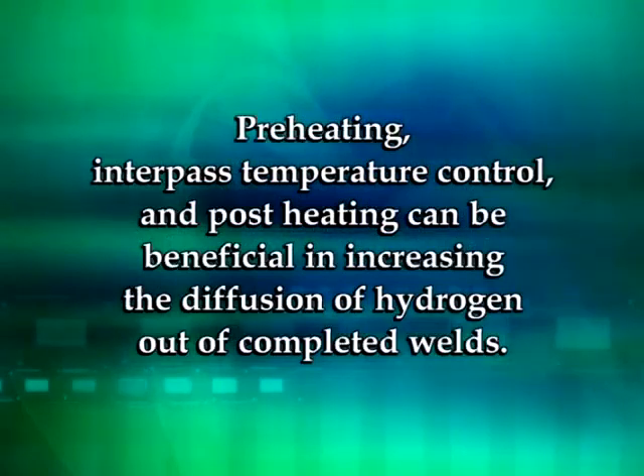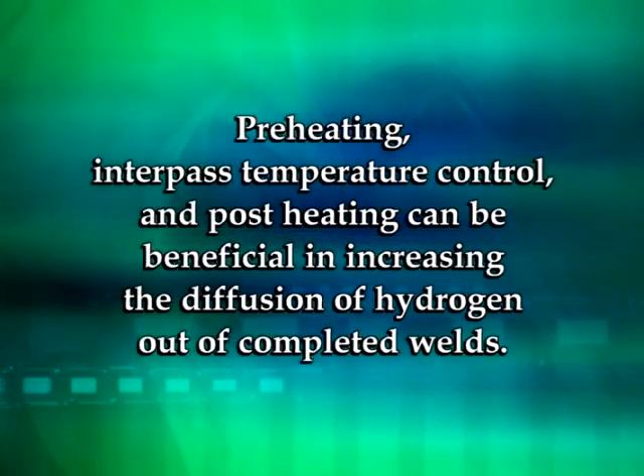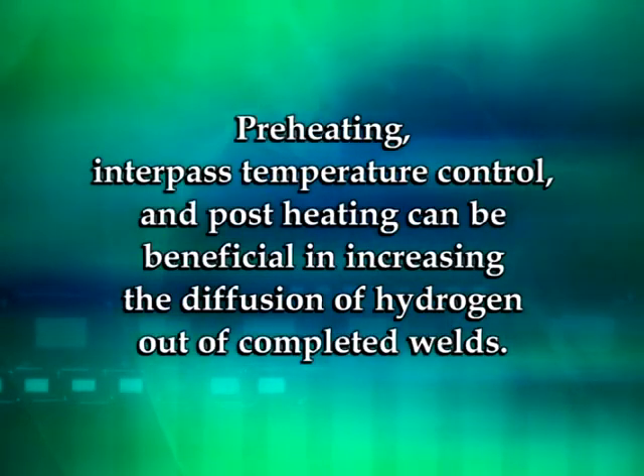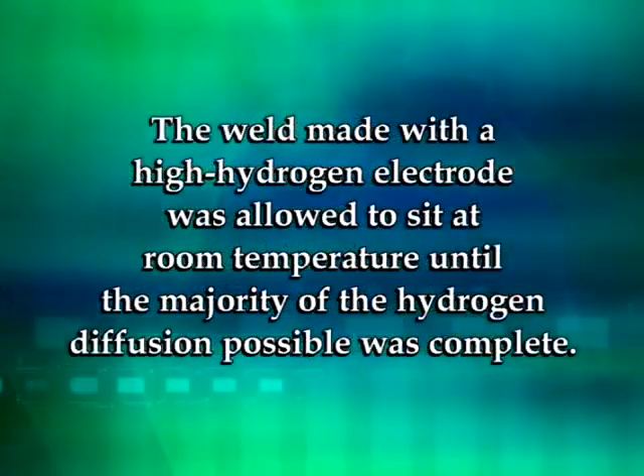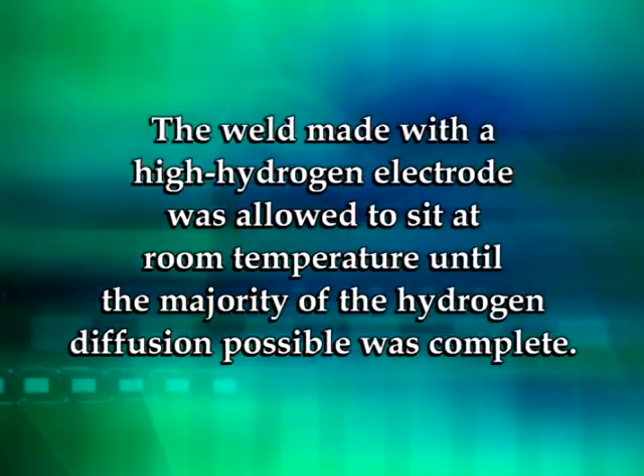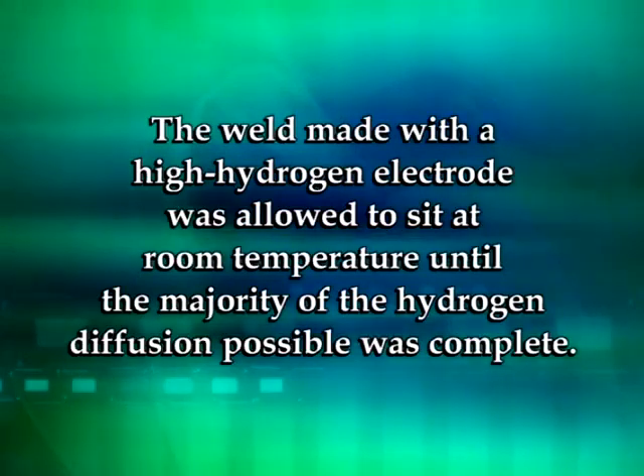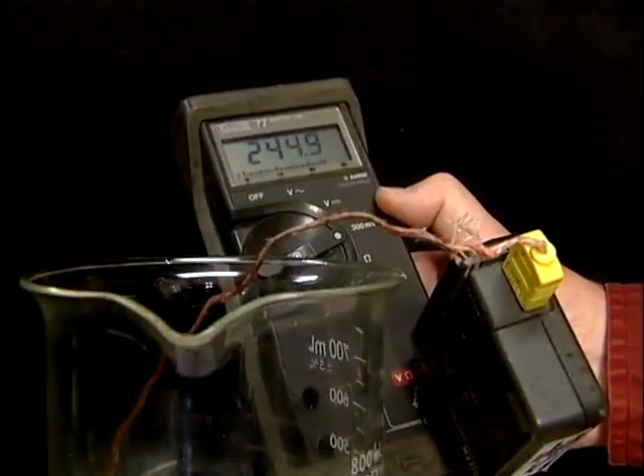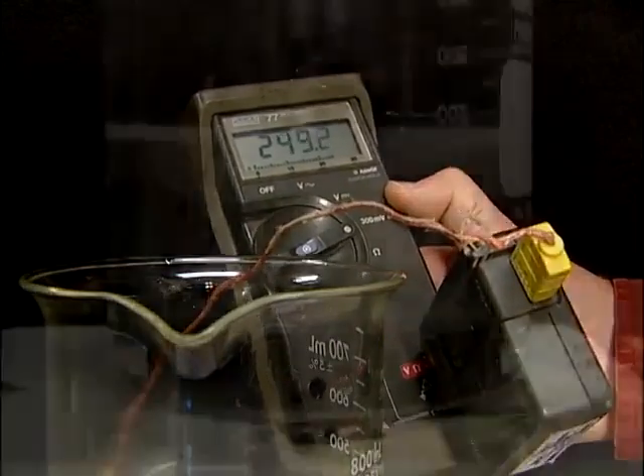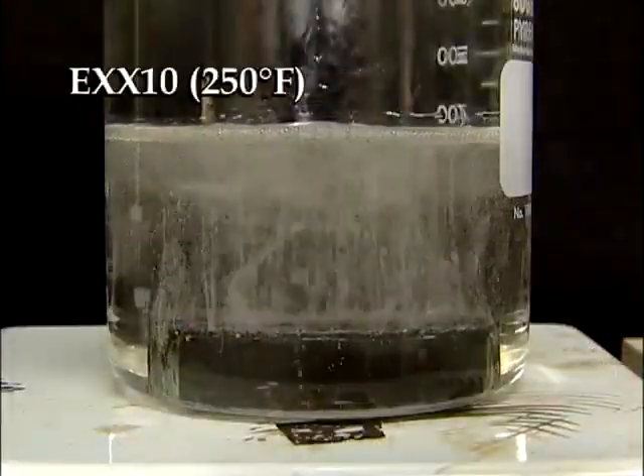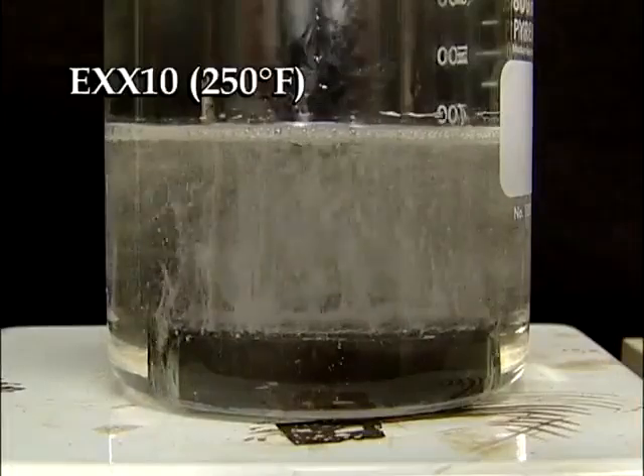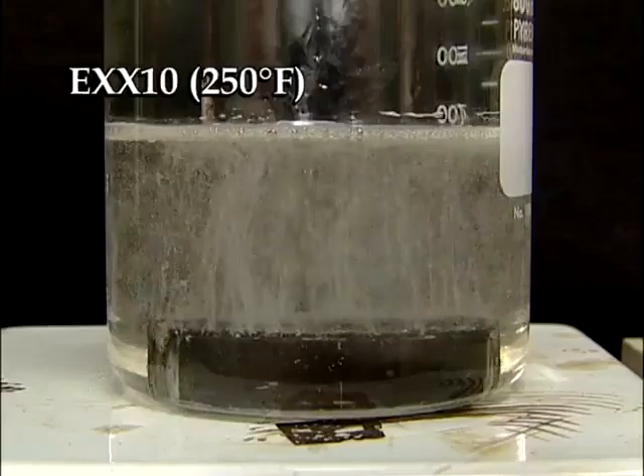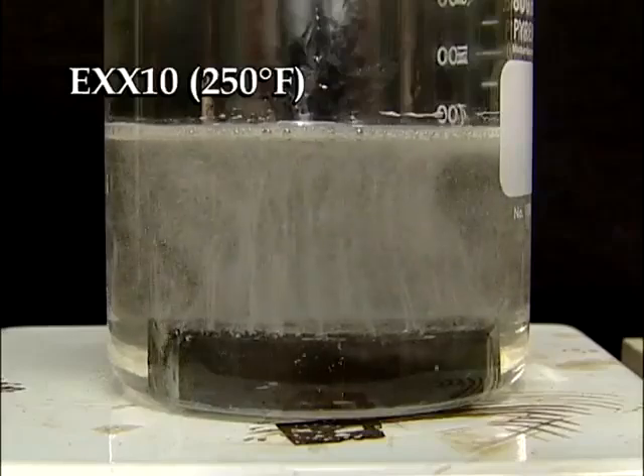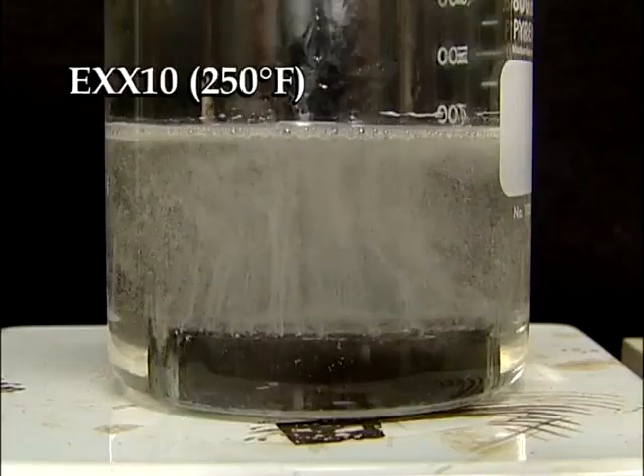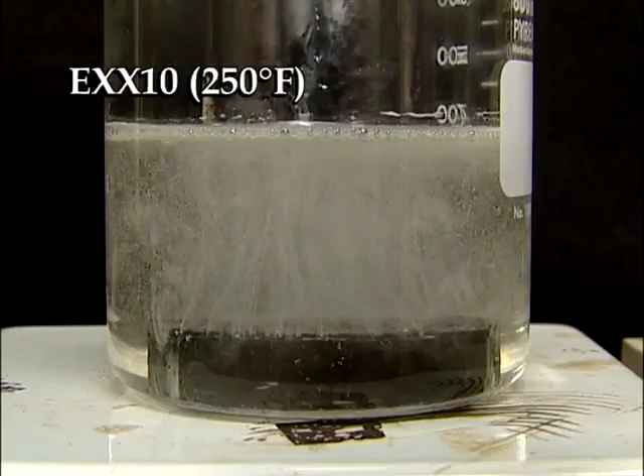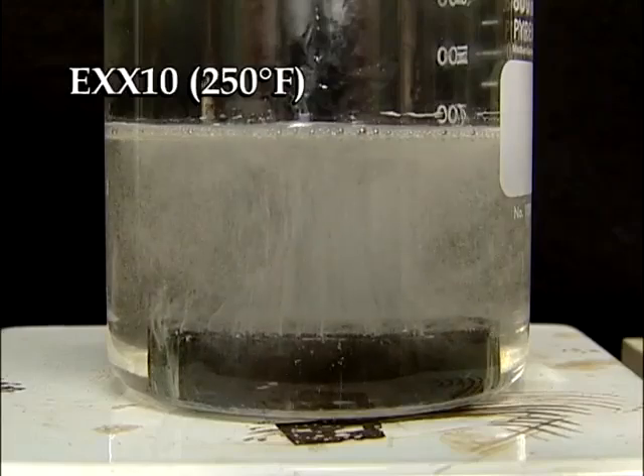Preheating, interpass temperature control, and post-heating can be beneficial in increasing the diffusion of hydrogen out of completed welds. The weld made with a high hydrogen electrode was allowed to sit at room temperature until the majority of the hydrogen diffusion possible was complete. When it is placed into mineral oil that is heated to 250 degrees Fahrenheit, a temperature that we showed allows hydrogen to diffuse 1,000 times faster than at room temperature, we can see that diffusion begins again and a rapid release of hydrogen occurs. Therefore, welds that are preheated and allowed to slow cool or post-heated will allow more hydrogen to diffuse, reducing susceptibility to hydrogen cracking.